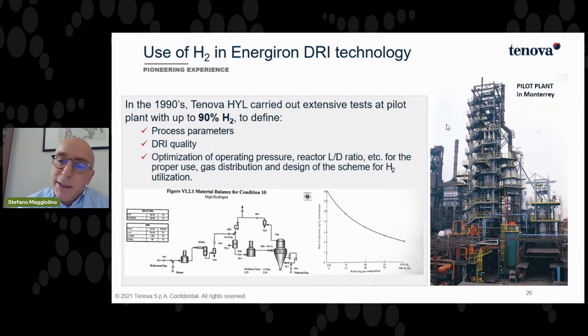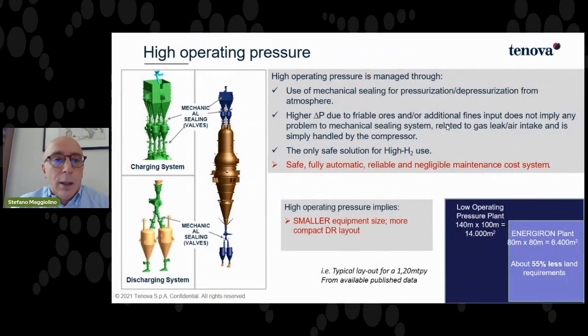In this slide, we can see the pilot plant where we did the test in the 90s, and thanks to this test, we're nowadays able to design a plant with the right process parameters, ensuring the DRI quality, and with the right design of the plant, particularly of the reactor. And as I was saying before, we have as a standard in our plant some mechanical sealing valves that are definitely necessary for a safe and fully automatic operation of a DRI plant while using hydrogen.